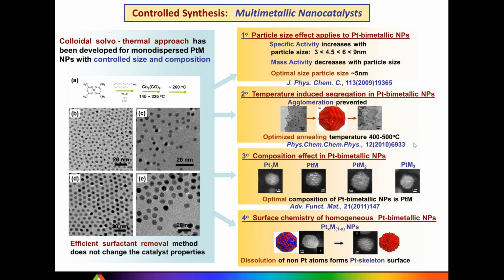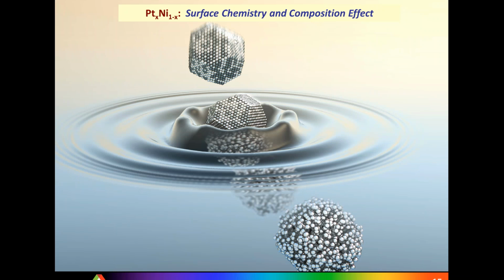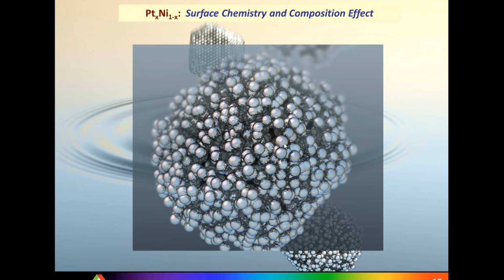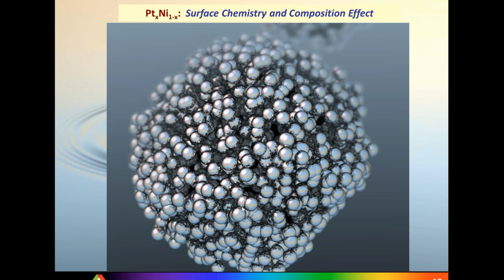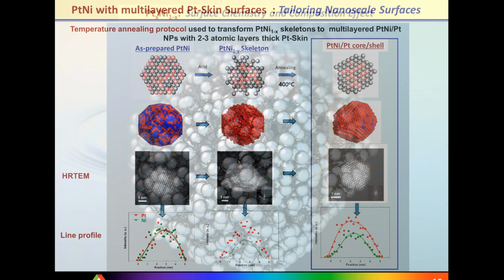And in reality, that leads to the following. So here is an example of a particle which is as synthesized, having platinum and nickel on the surface. But once we expose that to reactive environments such as acidic electrolyte, then whatever is the non-platinum component is being dissolved instantaneously. And that leaves a particle with a so-called platinum skeleton type of surface, highly corrugated with a large number of under-coordinated atoms, which are not desirable, as we could see from those durability studies. And certainly that was not the last step in our treatment of the catalyst.